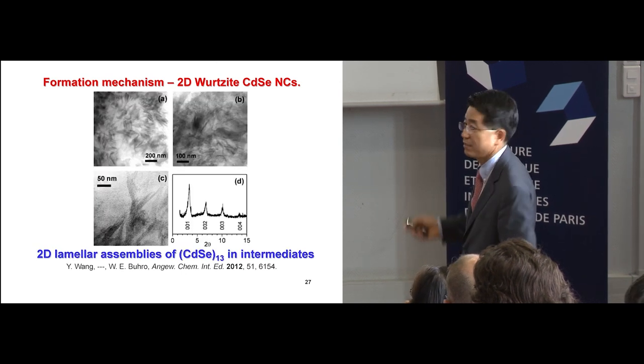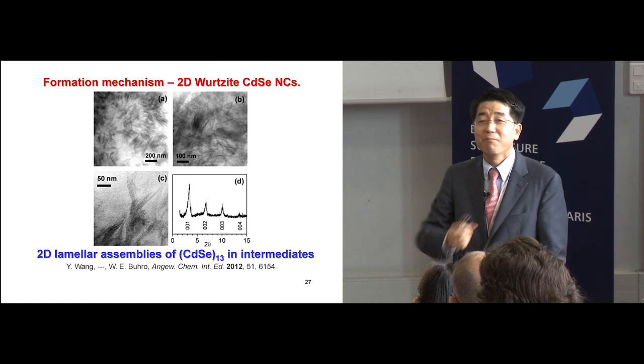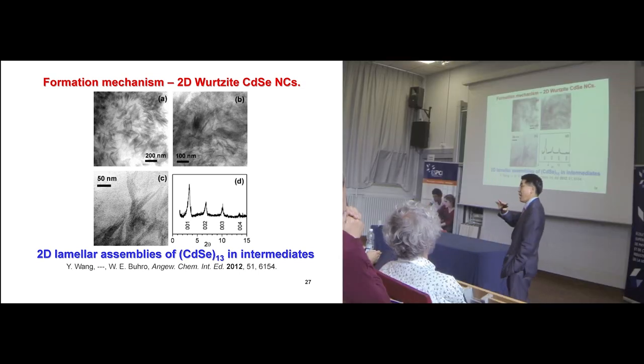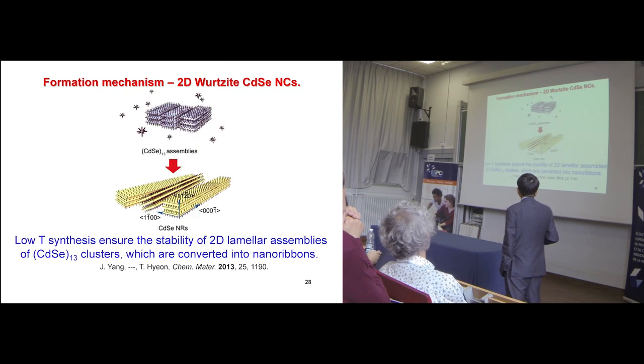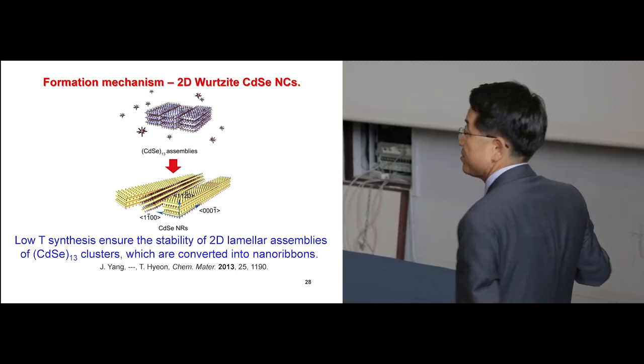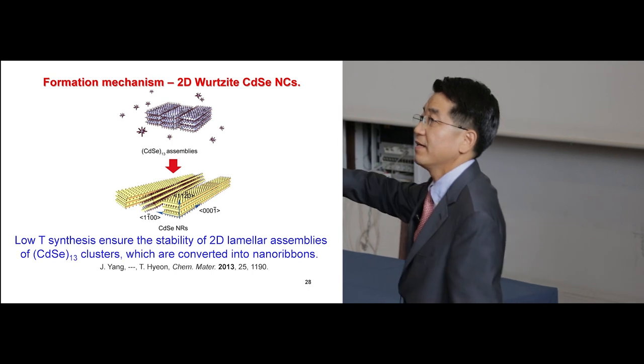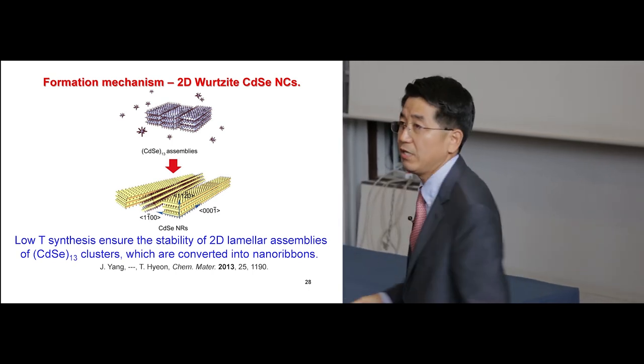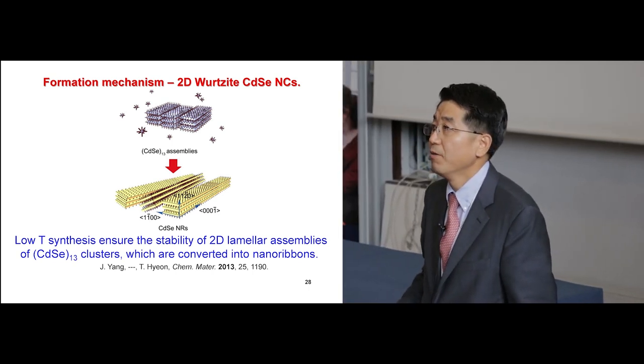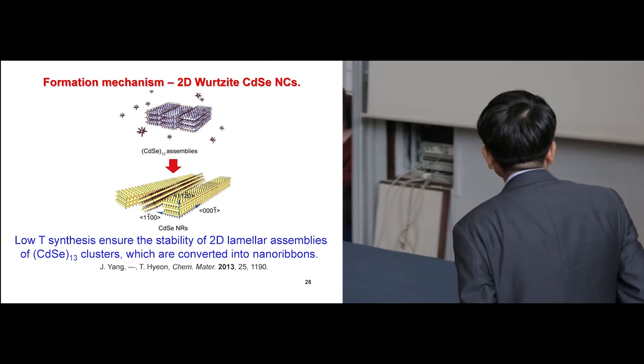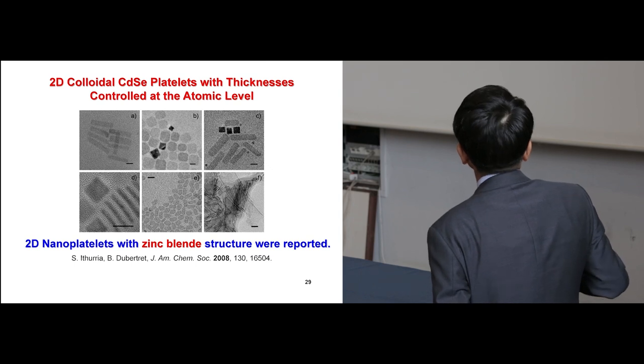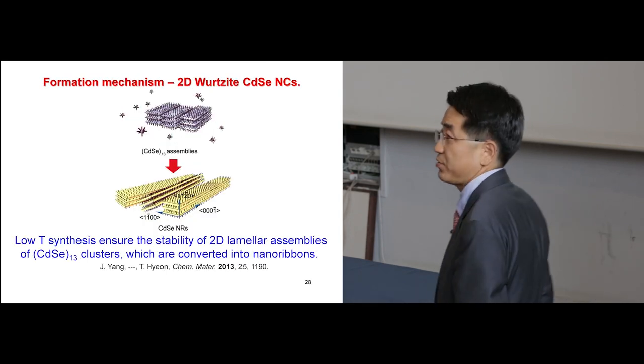And also, the clusters make lamella structures, as you can see here. They're aggregated and assembled to make these aggregate structures. What we think, and a lot of people think, is that first these CdSe clusters are assembled, and then lightened to make these two-dimensional, plate-like structures. So far, the material is wurtzite structure.